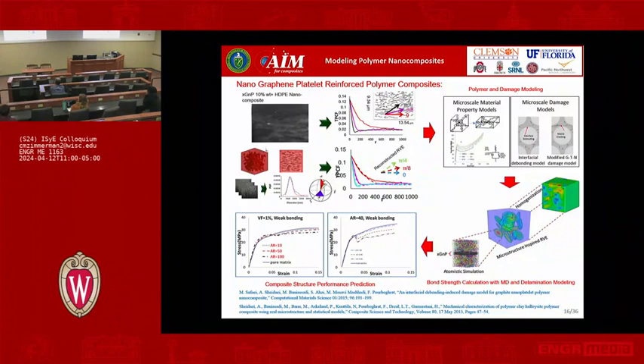So if you actually did the 2-point correlation function along this 0 direction, it would be back here. The volume fraction stays the same, but the distribution will be very different. If you do it at different angles, you get different, statistically different properties that come out of this thing.